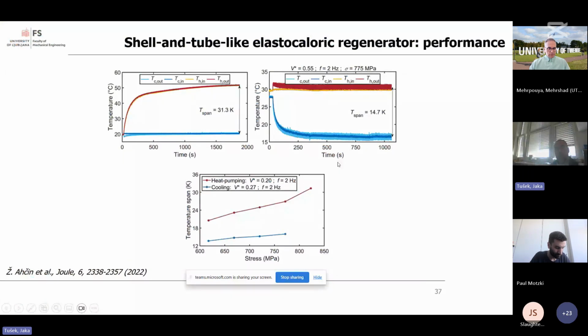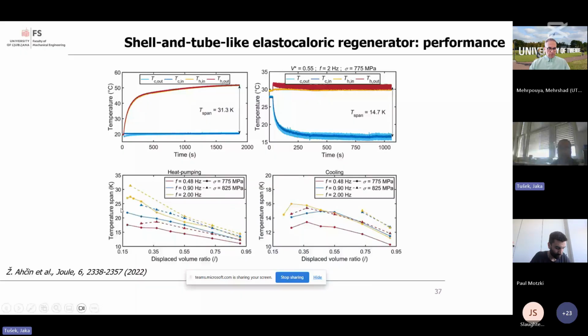We couldn't go lower because the AF temperature of our material was a bit too high for a cooling device, so we didn't want to go below AF temperature. We had tested this system at different, let's say, mass flow rates and different operating frequencies up to 2 Hertz. And then we tested the system also by adding the cooling or heating power.